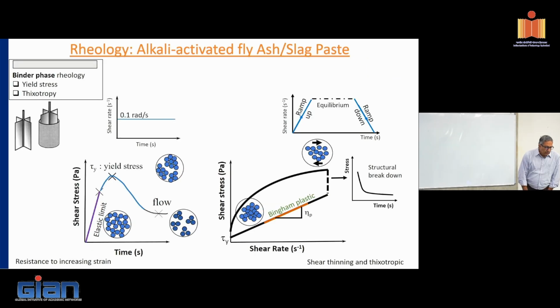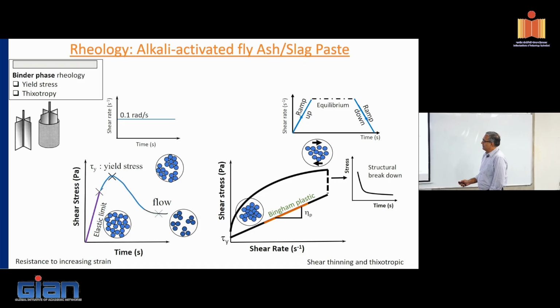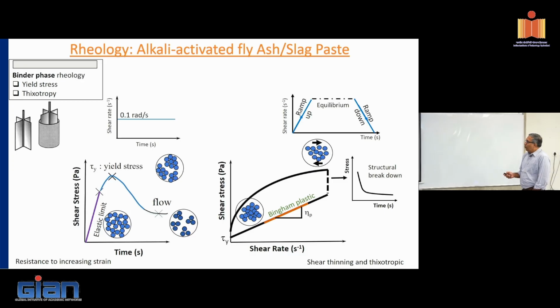Now, coming to the rheology, going back to the basics again. If we do the rheology, we'll stick to the standard test, a constant shear rate test, and yesterday you saw how to measure thixotropy. What we would do is basically do a ramp up. So we are ramping up in strain rate. Hold the strain rate constant for some time. What do we hope to achieve here? Basically smash the internal structure, complete whatever deflocculation we can achieve, and then ramp down and see what state we are left with.